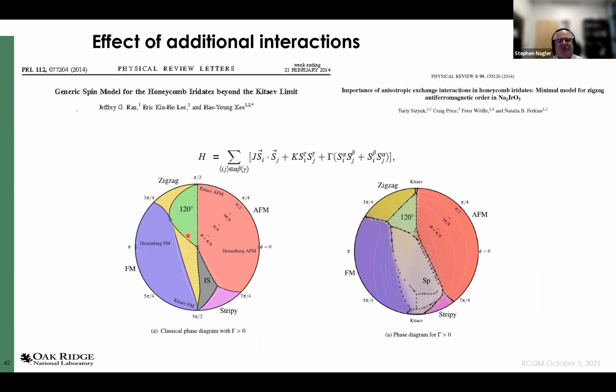And on the left is basically a classical phase diagram that was worked out by these groups, and on the right is a quantum phase diagram. And you can see that the zigzag and stripy ferromagnetic and antiferromagnetic ground states are still there, but you can also have the 120-degree ground state that's characteristic of sort of a Heisenberg antiferromagnet on a triangular lattice. You can have incommensurate spin ground states. And in the quantum limit, yes, the Kitaev quantum spin liquid ground state can survive with this Hamiltonian as well.